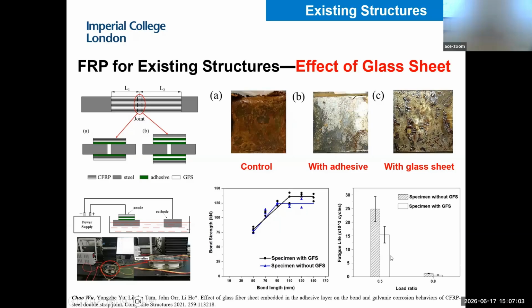However, if you do fatigue testing, the interface is negatively affected. From the fatigue results, the shaded bar represents the fatigue life of the interface without glass fiber, and if you use a layer of glass fiber, the fatigue life even drops by half. That means for structures like bridges, which are sensitive to fatigue loading, it's not recommended to use glass fiber to avoid galvanic corrosion, because it introduces defects in the bond line, and fatigue is very sensitive to defects—if you have defects, you have lower fatigue behavior.